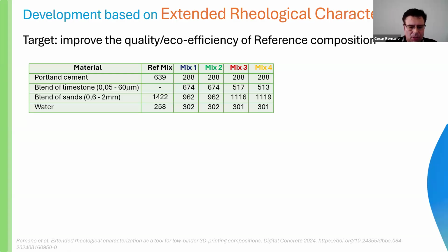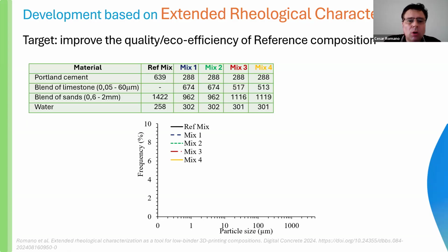In the printing concept adopted by this equipment, there was no pump stage. I need to say this because the material was mixed and directly fed into the print head, okay, and then forced through the nozzle. Once the rheological characteristics of this reference composition were understood, we initiated the development of more sustainable formulations, reducing the cement content to less than half of the original value.